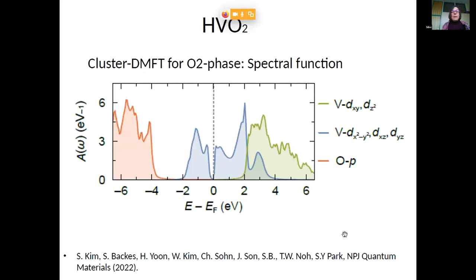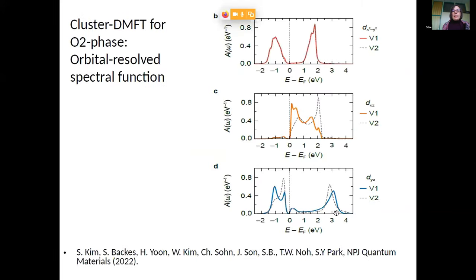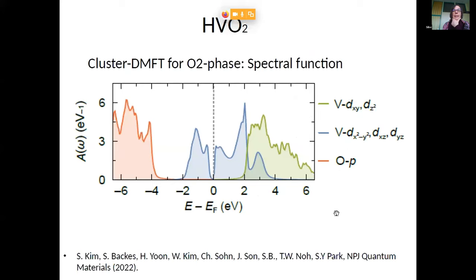Nevertheless, when we do the cluster DMFT calculation here, we indeed find within the T2G manifold, here in blue, opening of a gap, and here, as expected, oxygens and EG pi states. So the thing comes out as an insulating compound if you look at the theoretical spectral function. And now we have to analyze why is that the case. So how can we have an insulating D2 configuration here? And that is very interesting.